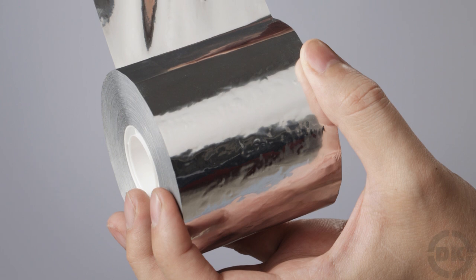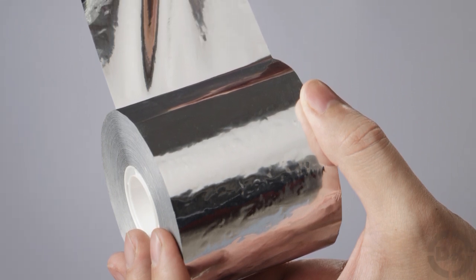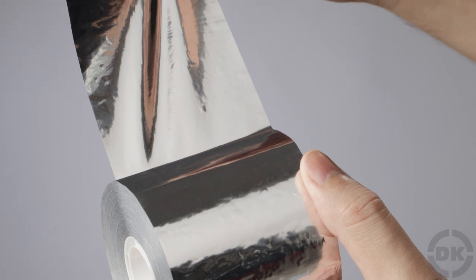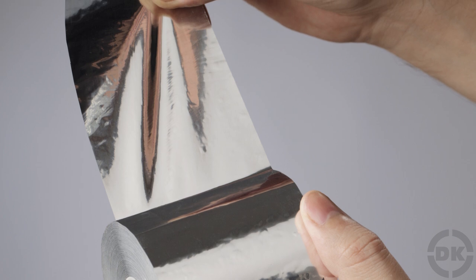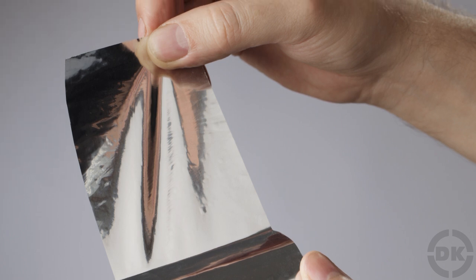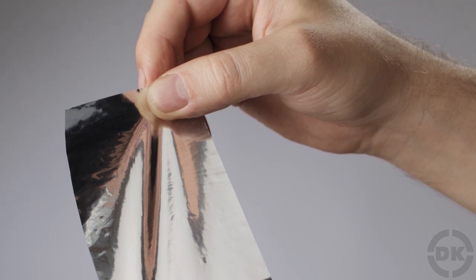This initial foil is sent through still more rollers several times until it reaches the desired thinness. For the type of foil that is bright on one side and matte on the other, it is so thin that during some of the last rollings, two sheets of thin foil must be placed together lest they tear or crimp during the final rolling. One consequence of this is that while the sides that touch the highly polished aluminum rollers are burnished to a bright finish, the inner sides that touch the other aluminum foil remain matte.